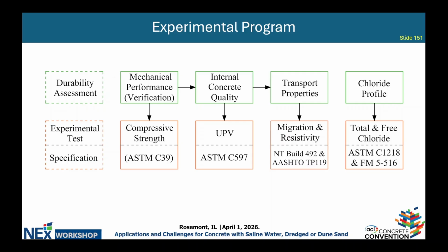And after that, we also ran the total chloride as well as free chloride content to determine the amount of chloride ingress as well as the bound chloride for this seawater system.